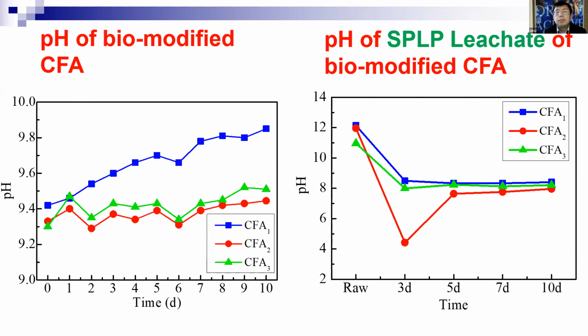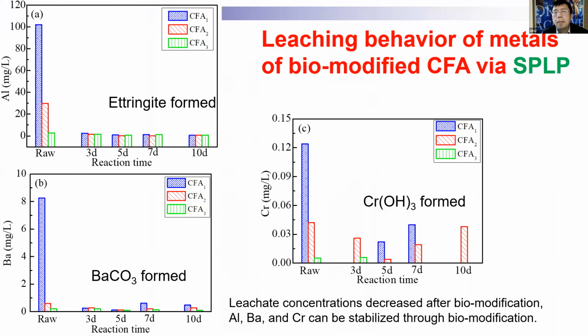So that's kind of like acid neutralization potentials to make the pH stabilize that. So for the metals, we looked at aluminum, barium, and chromium. When we looked at these three types of coal ash, as long as the reaction time, you can see almost all three types quickly decrease to close to 0.